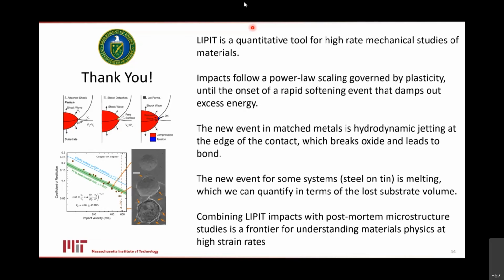And from Jonathan Lind, thank you, really nice work. You motivate that LIPIT can provide high strain rate strength data to address questions such as the upturn phenomena, which is directly a signature of the strain rate sensitivity of materials. However, the EPP scaling model you showed fit the data to a collection of tests where the characteristic strain rates are large and vary by a few orders of magnitude. How does quoting one strength or hardness value from the EPP scaling model over a large range of high strain rates remain consistent with the strain rate sensitivity picture of the material, especially at high rates, where the effect is even more pronounced? Yeah, that's a very smart question.